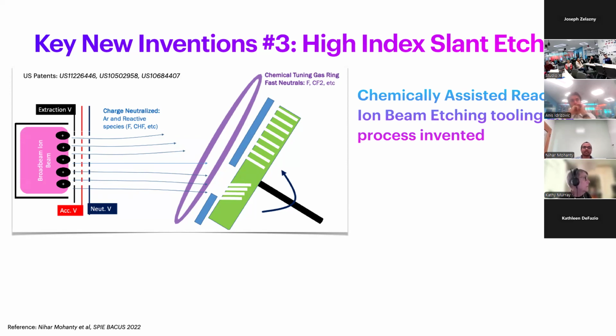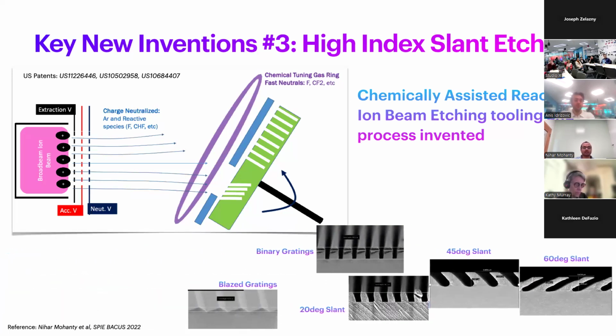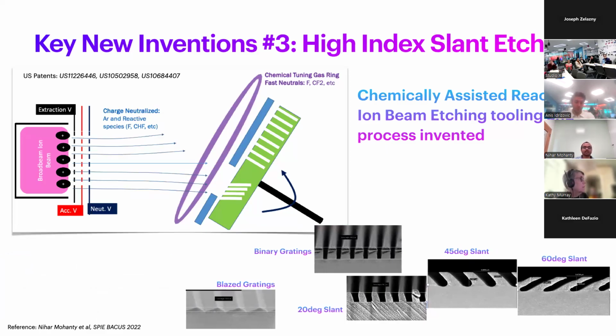When we started working on etched waveguides, the hardware that was available in the market wasn't good enough to produce slanted gratings at these various slant angles with different materials. The typical hardware available at that time either enabled reactive ion beam etch, where all your chemistry is inside the plasma chamber, or chemically assisted ion beam etch, where all your chemistry is in a gas ring that is in front of your substrate. We worked with our tooling partners to co-develop novel hardware and processes that enabled us chemically assisted reactive ion beam etch to enable multiple different types of grating unit cells, starting all the way from binary to blazed to over 60-degree slant, with a high degree of symmetricity, which has significant impact on the final optical performance.